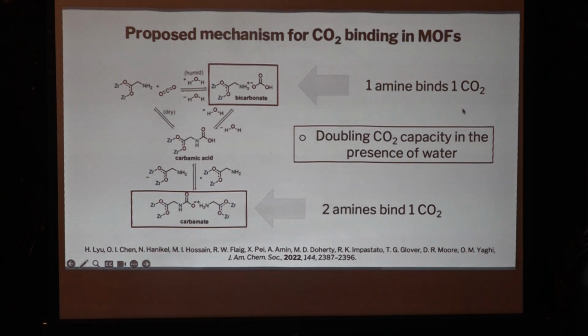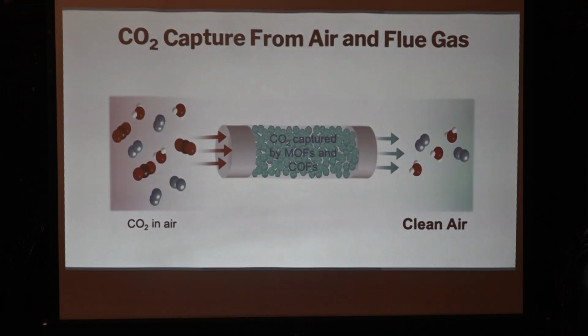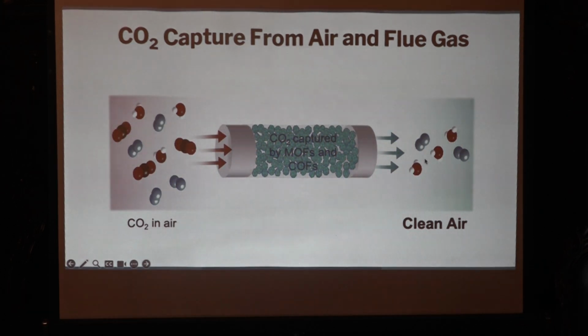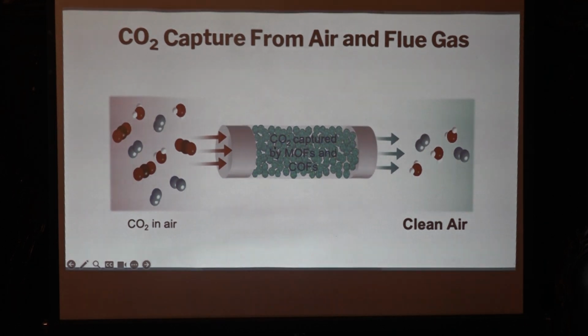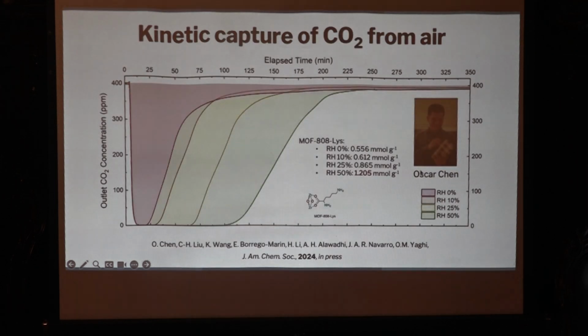And the ultimate test of whether your material is working or not comes from what we call breakthrough experiments, or by doing kinetic separation, where you have your material in a column, you expose it to air, and you look at what comes out and when it comes out. Okay? And in this case, you can see that this column captures the CO2 and leaves you with clean air. But this is the result. This is the data. So this is for MOF 808, the MOF I just showed you with the rotation. And instead of glycine, we have functionalized the pores with lysine. Lysine is more basic than glycine, so we anticipated that it would do better than glycine.